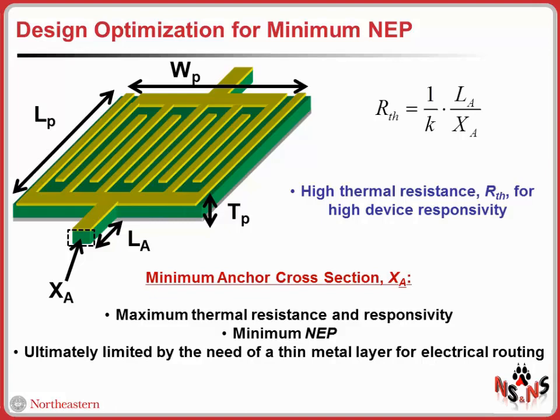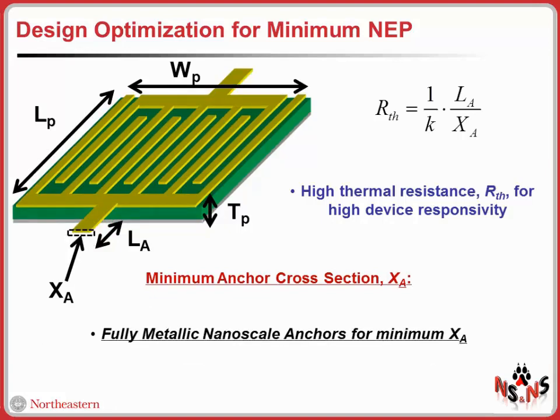So in general, in order to maximize the thermal isolation, it would be needed to basically minimize the cross-section of these anchors. But the cross-section of this anchor is really limited by the need of a thin metal layer for electrical routing. So we need to provide an electrical routing from the device terminal to these electrodes that are patterned on the resonant body of the device. So the design solution that we propose basically involves removing the piezoelectric layer from the anchors and using very thin nanoscale anchors with a minimum cross-section to anchor the device to the substrate and simultaneously provide the electrical routing needed for the signal. So this really minimizes the size of the anchor and maximizes the thermal resistance.